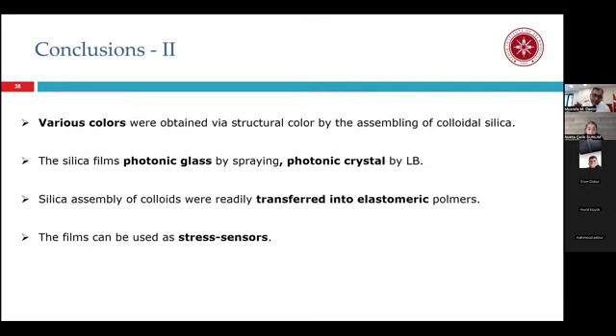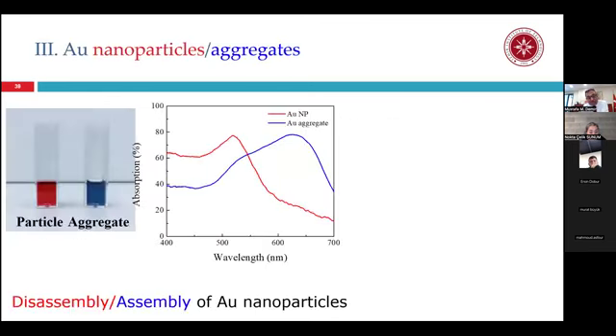For the conclusion of the second part of my talk, we obtain various colors via structural coloration, and using spraying and Langmuir-Blodgett, we obtain photonic glass and photonic crystals respectively. They were readily incorporated into transparent elastomeric polymers, and they can be used as a stress sensor, as you witnessed. So the last part of the talk and the last chemistry I want to talk about today is gold nanoparticles. As I said at the very beginning, bulk gold has a yellow color. So when we reduce the size to, say, 10 nanometers, we have surface plasmon resonance. We see collective oscillation of electrons in the structure, upon application of an electromagnetic wave.